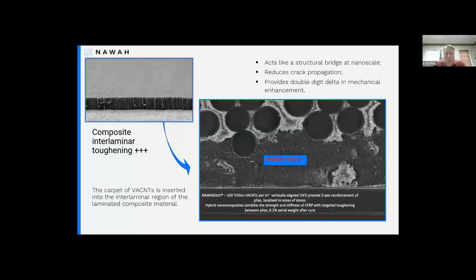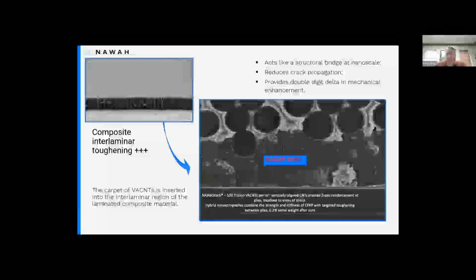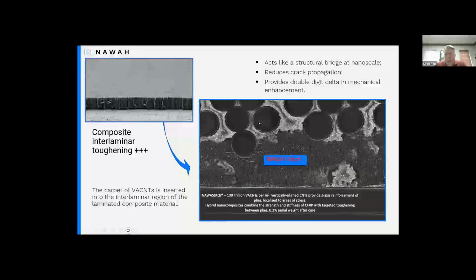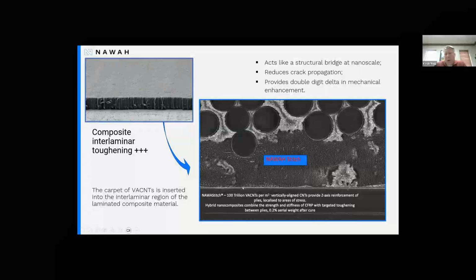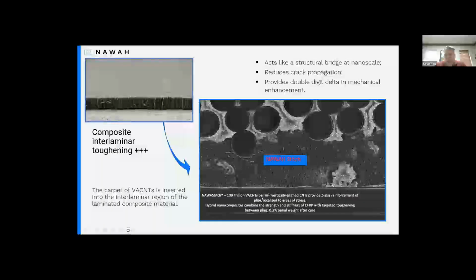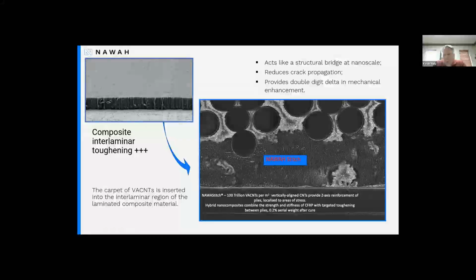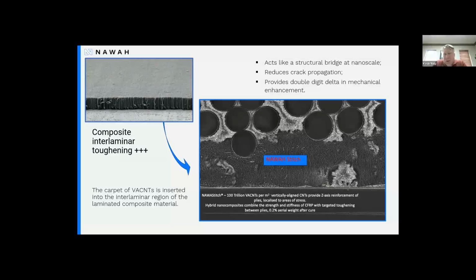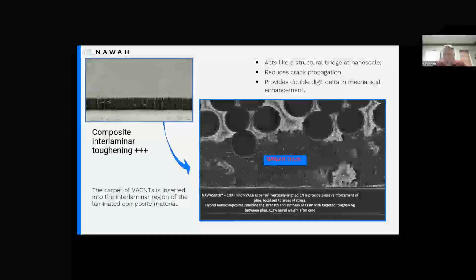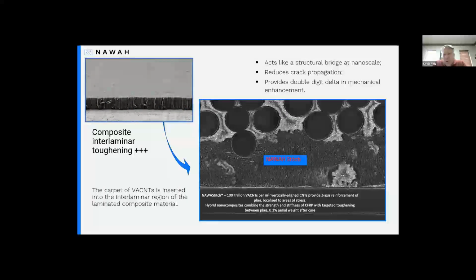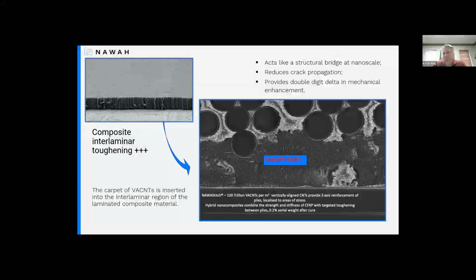So we grow the vertically aligned carbon nanotubes, so what? Why? The picture on the bottom shows it best. We have a ply of carbon fiber coming out at you, and we have one carbon fiber going across the bottom of the picture. In between, you can see the vertically aligned carbon nanotubes. We create that structural bridge from ply to ply, fiber to fiber. So we're creating that structural bridge.